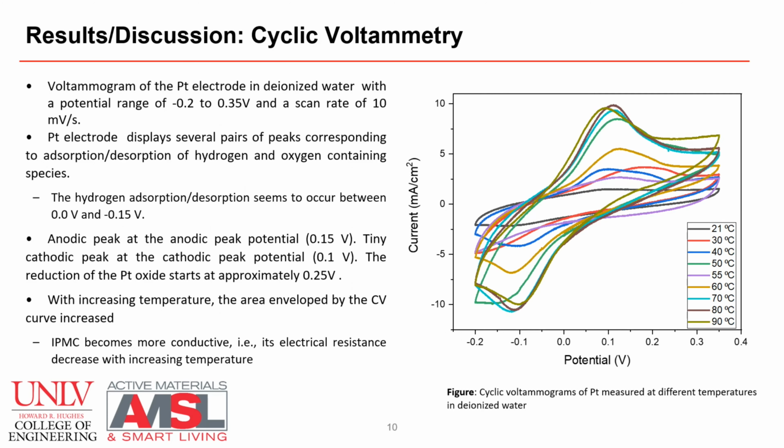The electrochemical phenomena of the electrode surface of the platinum IPMC is an essential factor when interpreting the fundamental characteristics of the IPMC. Based on the principle of IPMC actuators, a chemical reaction on the cathode surface is expected to affect the deformation properties. This is due to when a small amount of voltage is applied across the electrode, the cations bind with water molecules, generating a higher density of water molecules on one side of the membrane, converting the electrical potential into mechanical work through actuation.